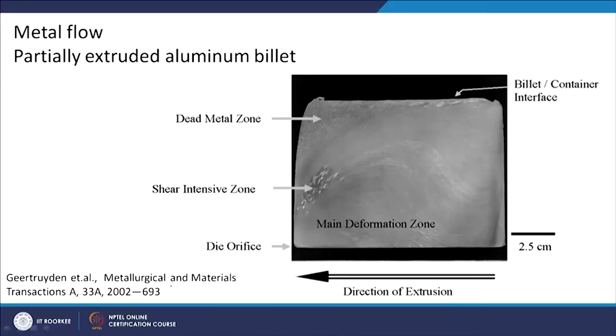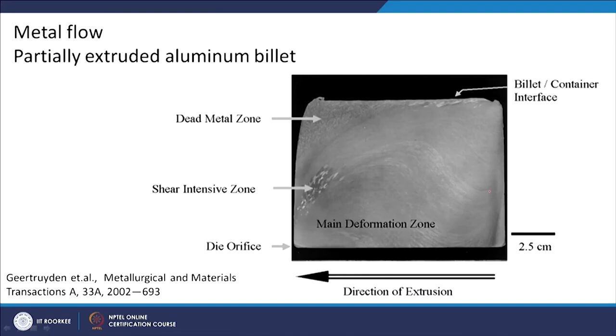If you want to see how the metal flows during this kind of extrusion process, this is one example again taken from a literature. You can see what they have done: they started the extrusion process, stopped it, took the billet out, and cut it in half, and then they are trying to show how the material flow has taken place. As you can see here, this is the dead zone. You don't see any microstructural change here.